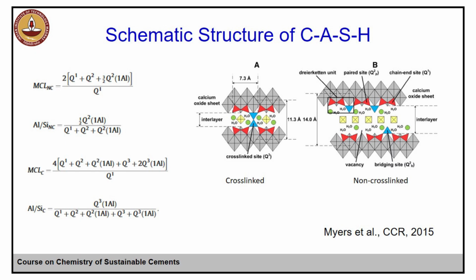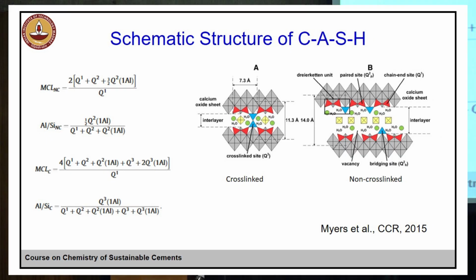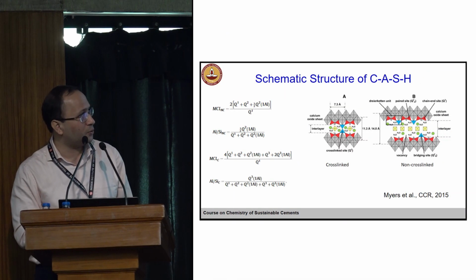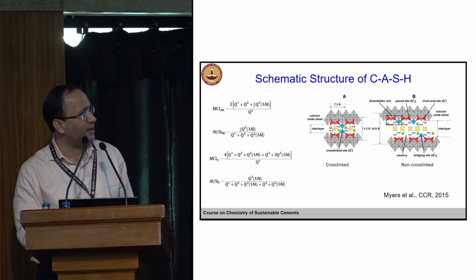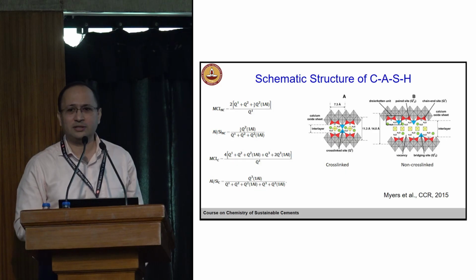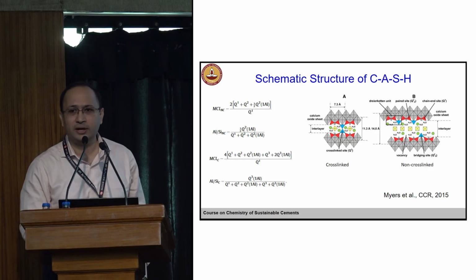So depending on the type of CASH, calcium aluminosilicate hydrate, whether it is cross-linked or non-cross-linked. I am just showing you both. This is a cross-linked one, right? So these sheets, these are calcium oxide layers, and on this you have a silica tetrahedron, right? This is another calcium oxide layer, and you have a silica tetrahedron. So it could be cross-linked, and in this case you have a non-cross-linked. And between these layers you have ions, like alkali ions, you can have water molecules present between these layers. That's what we call interlayer water.